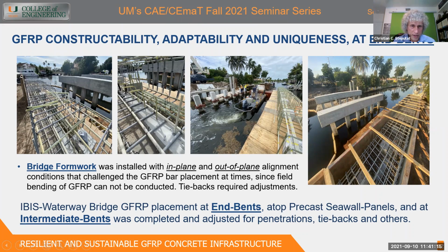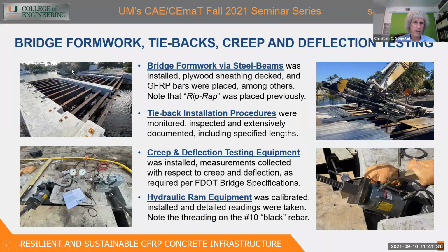But you can see here, all these are GFRP bars, different types. And so they were all installed, and they were actually in 2 different dimensions, which was tricky because we had in and out of plane bending, which required bars to be cast since we can't bend them on site. On the left here, real quick, we essentially have steel supports. You see here our substructure in place, and we're going now to the superstructure, which is our deck.